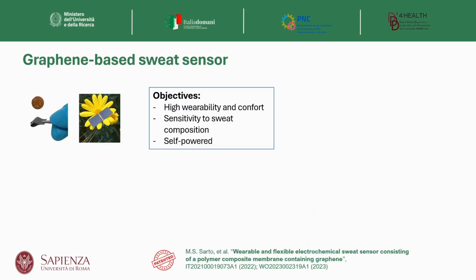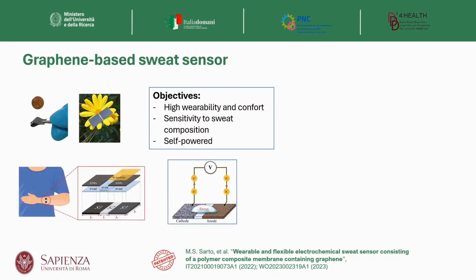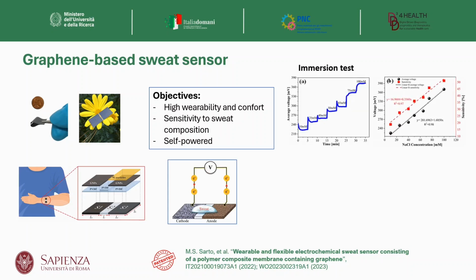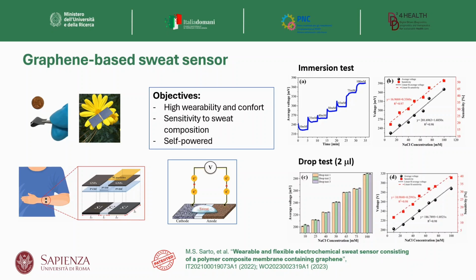And finally, this is the sweat sensor. Actually, you see, it's just a very thin foil of material. Again, the technology always combines polymer, PVDF-based polymer, and graphene in some way. And the sensor is self-powered. Basically, it is an electrochemical cell. But the main point is that the signal is proportional to the content of salt. We made immersion tests in which you see the signal proportional to the salt content. You can see the linear response, but also in the drop test with just 2 microliters of fluid, we can detect a very good signal as shown here.